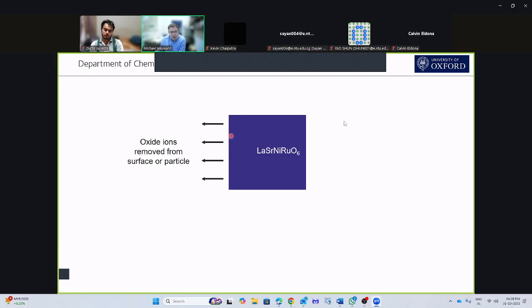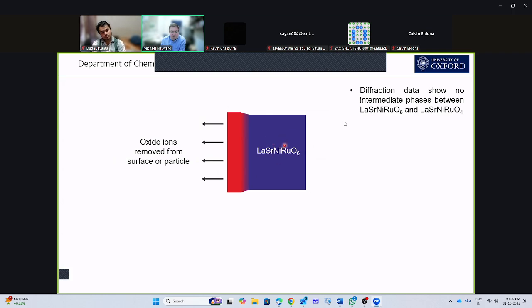And so what we're going to see is that the oxide ions leave the system from this surface to make an oxygen deficient region here. Now, what we see in our diffraction data is we actually don't see any intermediates between the fully oxidized O6 form and the reduced O4 form. And so what we have between these two compositions is a very sharp interface. We get a very sharp change in oxygen content at this position here.